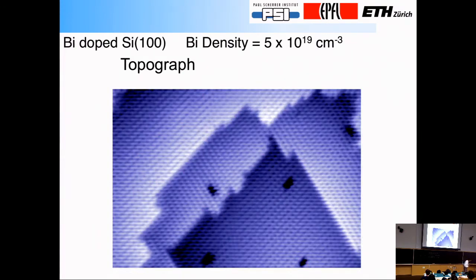So now, how do we know that this is real? Of course, this kind of thinking is very old. But at that time, one had no way to directly check that. Fortunately, in the intervening period, people discovered scanning tunneling microscopy. I'm going to show you here that we can find some very big atoms in a doped silicon wafer. This is a doped 100 wafer. This is an STM image of that wafer with a fairly high but not too high density of bismuth atoms, so enough that we can pick up a few when we do scanning tunneling microscopy.